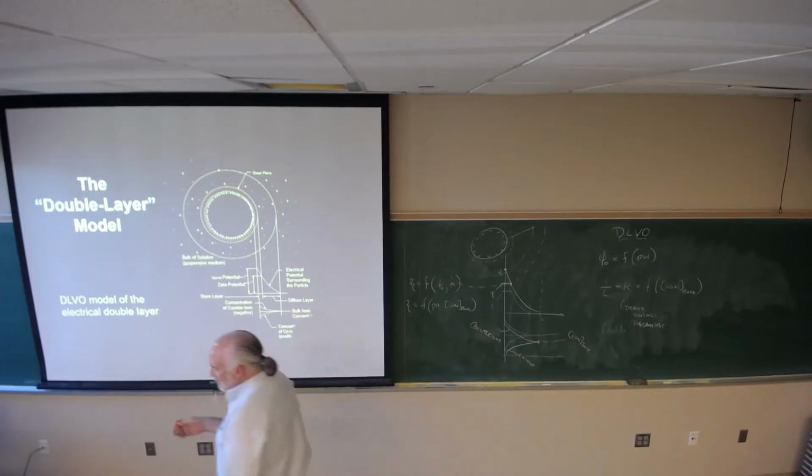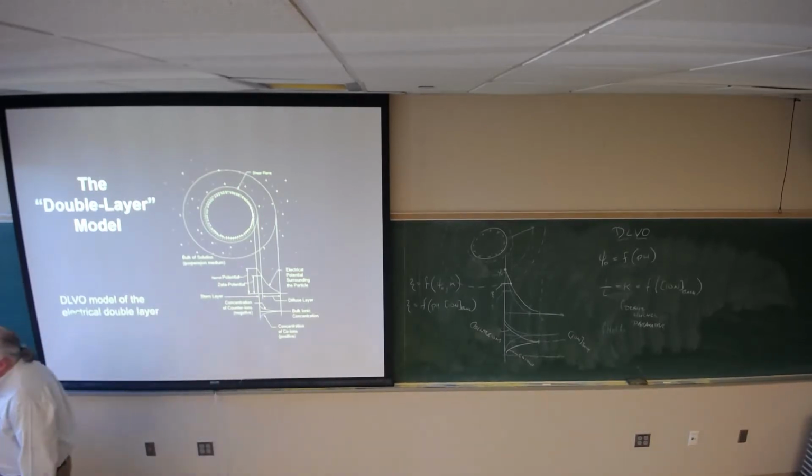If I am already below the point, let's say, would you say decrease the pH? So if I'm already below the point of 0 charge in terms of pH, and I decrease the pH, then my Nernst potential increases. Okay? As I move farther away from the point of 0 charge, my Nernst potential increases. If I increase the pH and I'm moving away from the point of 0 charge, my Nernst potential will increase.